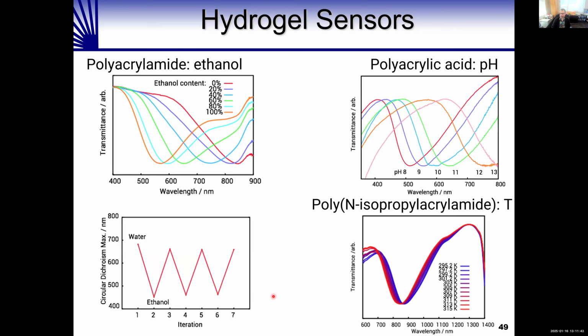We extended this concept to other hydrogels. We can make polyacrylic acid hydrogels, and now the color of the film is determined by the pH of the solution. We just dip our hydrogel into the solution, and by observing the color change, we can tell what the pH is.